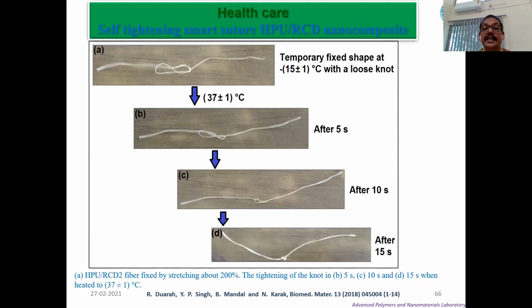This switching system, which I mentioned from literature, we have tried to replicate by using a hyperbranched polyurethane reduced carbon dot nanocomposite. Carbon dot and reduced carbon dot are biocompatible, and bio-based polymers also show biocompatibility from cell viability tests. The knot we produced addresses a major surgery issue: it's difficult to get the right tightness, either too loose or too tight, both causing delay in healing. So the right knot can automatically form with help of this smart attribute of the polymer, and since these are biodegradable, there is no need for second surgery. At body temperature of 37 degrees centigrade, after 15 seconds, it can form the knot as desired.